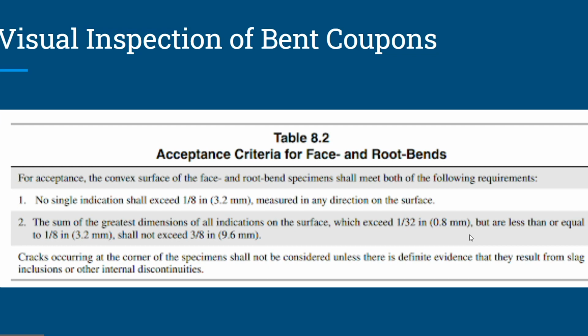There could be 30 of them. We don't count them. But if it's bigger than a 32nd of an inch and not more than 1/8, then we take all of those and we add them together. And if they add up to more than 3/8 of an inch, then the bend fails. If it's less than 3/8 of an inch, then the bend passes.